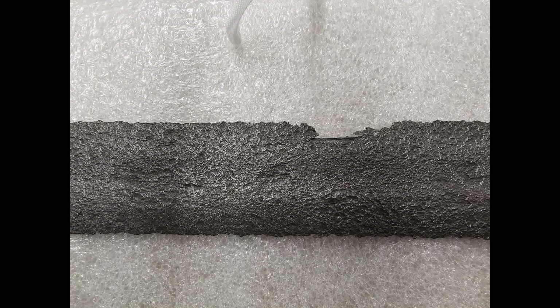The core area of the sword, the inner area of the sword, shows an elevated arsenic concentration, while the edge steel and also the outer surface, the outer layer of the sword, doesn't show any response in arsenic. This makes us believe that the core area is made of a bloomery type of iron, while the edge steel and the outer surface panels are more refined by a steel making technology.